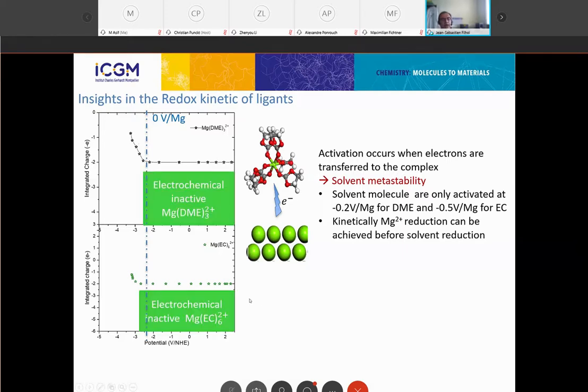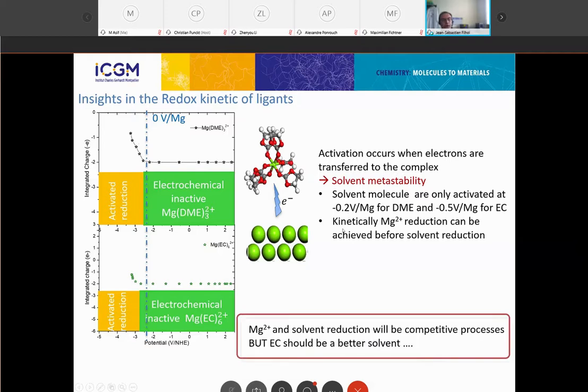So it allows us to identify the electrochemically inactive magnesium 2+. And when electrons start to be transferred, starting to activate the solvent reduction, it gives us the active reduction, where certainly all the dimerization and fragmentation are going to happen quite fast. So because of that, you see that the blue line is the potential of reduction of magnesium.